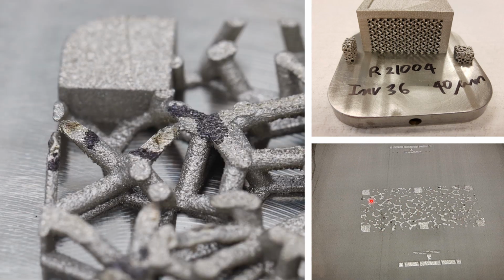So we went ahead and went full scale. This is now 250 millimeters across, but we also replaced the support structure underneath this table with the Voronoi lattice, and you can see now in this build here, this is what an unhappy build looks like. These parts sticking up, cuts to the recoater. The structure is very unhappy, and indeed we had to stop this fairly early on because the Voronoi lattice, while it appeared to be okay at this scale here on the top right, by the time it was scaled up, overhangs that maybe were only 1 or 2 millimeters here had now become 4 or 8 millimeters, and the part was very unhappy, as you can see.